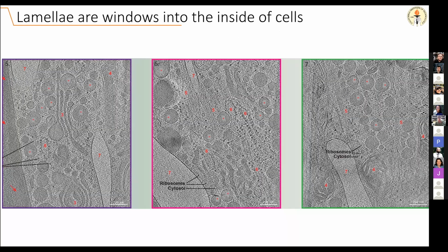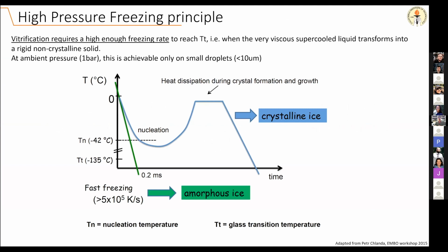And here I show examples of tomograms acquired in such lamellae, where we can see all the different organelles that are in the cell. And so FIB milling gives access to the inside of cells that are usually too thick for direct observation. So now, a little bit more difficult, we have a sample that is too thick for plunge freezing, and therefore too thick also for direct observation. So in these cases, we need to do something called high pressure freezing.